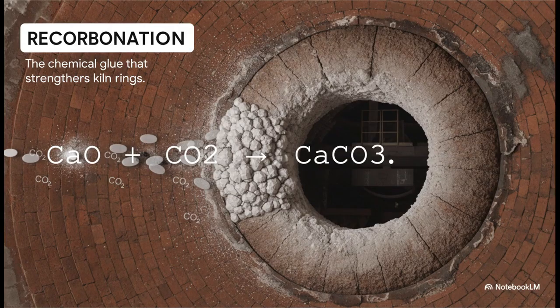And that hardening reaction? It has a name: recarbonation. It's just the reverse of the main calcination reaction we want in the kiln. Our good lime, the CaO, reacts with CO2 from the flue gas and turns right back into calcium carbonate. But in this case, it's not lime mud anymore. It's basically cement. It's the binder, the glue that gives that ring its incredible concrete-like strength.